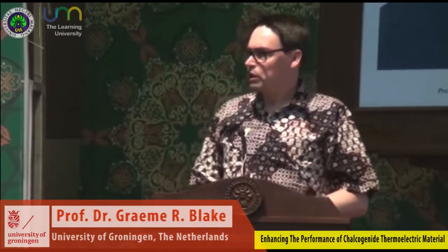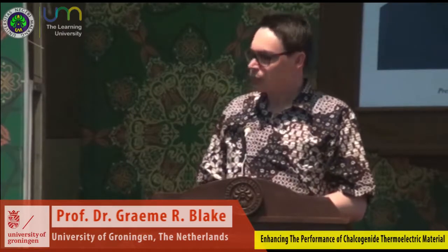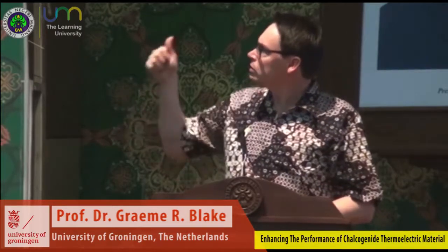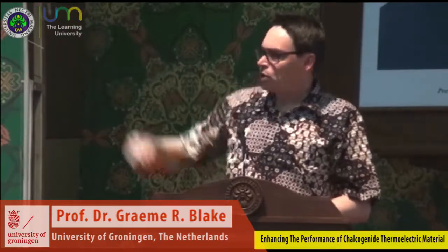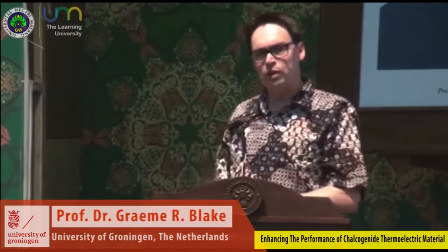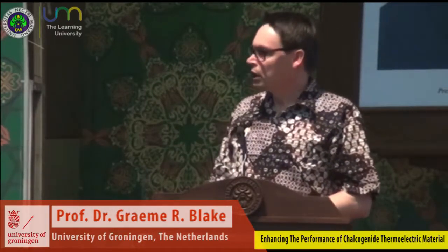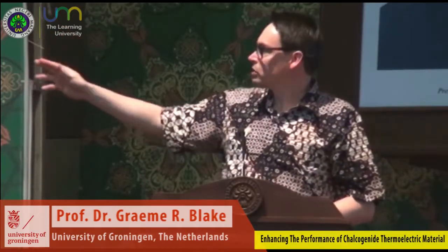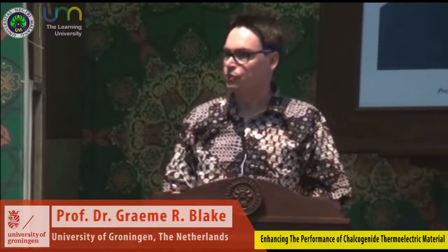So in our lab in Groningen, we've been working a little bit on various tellurides, and I'd just like to show some results of our own research pretty briefly. We've been working on this system here, which is known as TAGS. It's another acronym for tellurium, silver, germanium, antimony. So the chemical formula is shown on the top left here. It's a well-known thermoelectric. It's been known since the 1960s, and it's used in the Mars rovers currently. It's a good thermoelectric, among other things, because it has a complex domain structure shown in the electron microscope image on the left. It has this typical zigzag type of structure. Next, please.